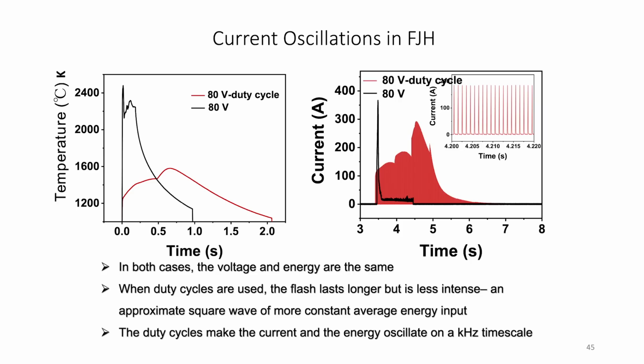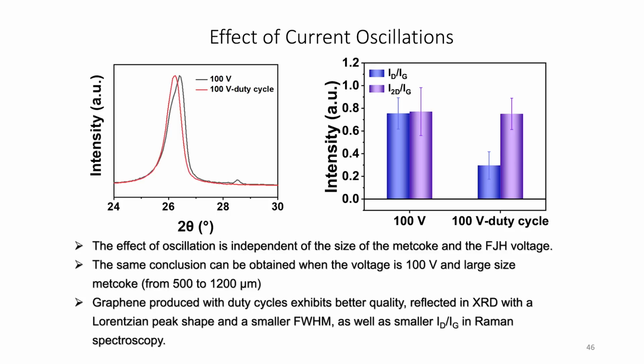We've looked at the current oscillations. If we have this kilohertz pulse, you don't have to put in as much energy. You get something that looks a little bit more like a square wave, and here's what this duty cycle looks like if you expand on it. This actually helps the material to order in this way. If you have 100 volts with duty cycling versus just 100 volts, you get a sharper Lorentzian, so you get a cleaner material. Here's 100 volts, here's 100 volts with duty cycle.